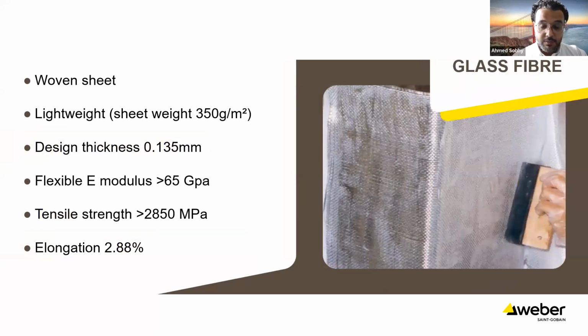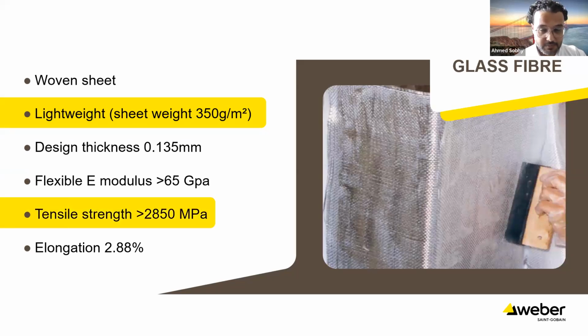Moving on to the properties of the glass fiber, not really dissimilar from the carbon fiber that we've seen previously. We're talking about a sheet weight of 350 grams per square meter. We're talking about a tensile strength of 2,850 megapascals.